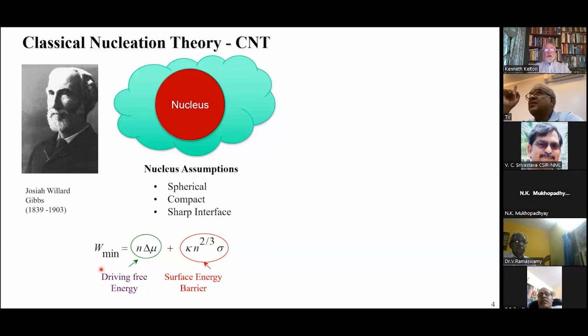Given that, he argued that the thing you need to focus on is the minimum amount of work required to form this nucleus. And because of his assumptions, he argued that it would be given by a volume term, which takes into account the driving free energy, in this case written as delta mu per atom, and a surface energy barrier term. This was the origin of the barrier that Fahrenheit discovered in his classical studies of water.